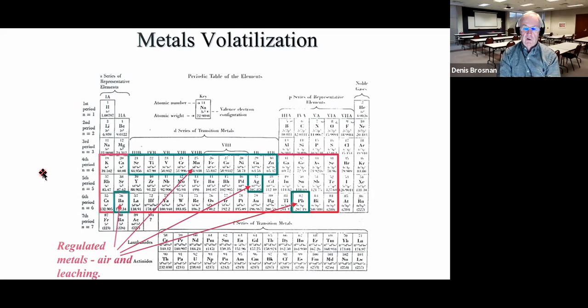In another case, an environmental agency in one part of the country called me up and said, we found chromium in soil samples around a kiln exhaust in a ceramic operation. And they seem to be pretty close to where the stack exhaust is in geometry. I mean, they were pretty close to where the stack was. And toward the property line, there were very little chromium. They said, what's this? And I said, well, that's vaporization of chromium in the kiln. It comes out of the stack. It doesn't go very far because it's really heavy. And so that was metals vaporization.